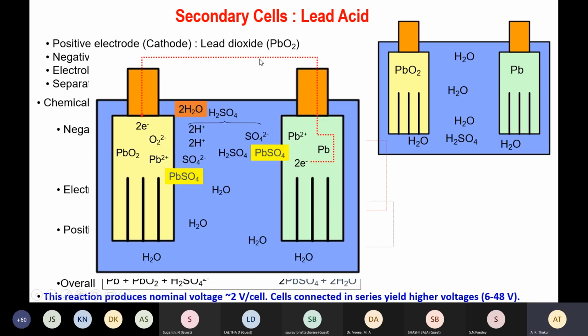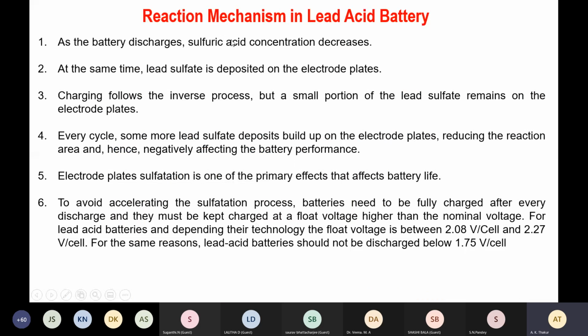The reaction that is occurring in a lead acid battery is demonstrated over here, as I explained already. As the battery discharges, sulfuric acid concentration decreases, and at the same time lead sulfate is deposited on the electrode plates. Charging follows the inverse process, but a small portion of the lead sulfate always remains on the electrode plates, and this causes sulfation of lead acid cell electrodes, which we will discuss in detail later.